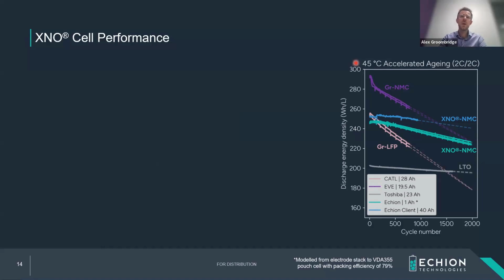quickly as we can. And what we've done is we've tested some of the most recent CATL cells, EVE cells from China. So graphite NMC, graphite LFP at a 2C rate at 45 degrees. And you can see, obviously, the NMC is higher energy density, the LFP chemistry is lower, but both degrade at a similar rate under these temperature conditions. So it doesn't take long for them to degrade beyond the point of not being able to use them for these applications where we need these longer cycle life.